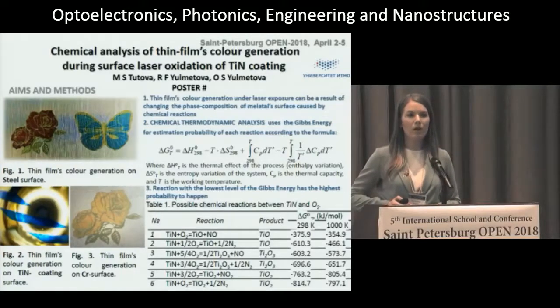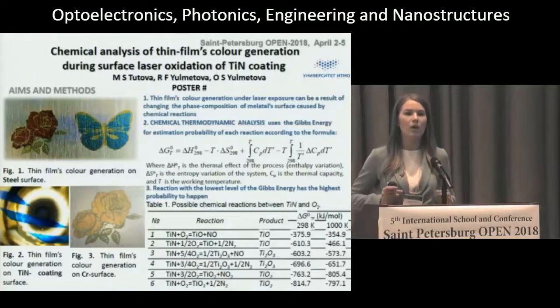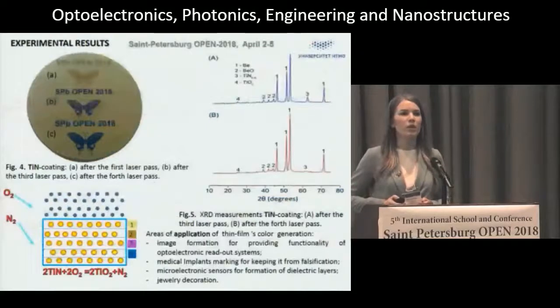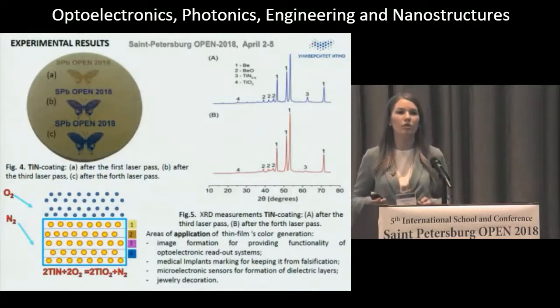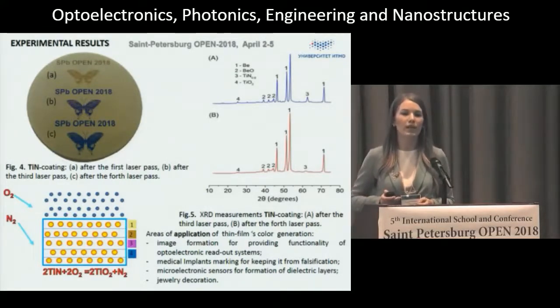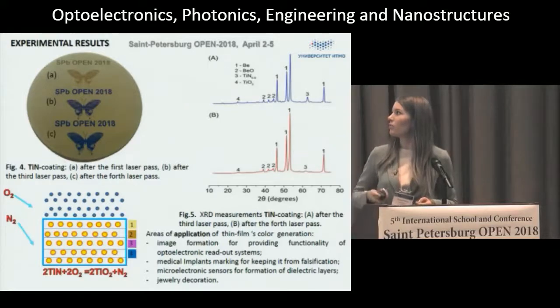According to this method, color generation can be described by a chemical reaction, and the formation of the most probable compounds has the lowest level of Gibbs energy. We tested our method on a titanium nitride coating, and the results of our calculations are in good agreement with the phase compositional analysis. During experiments, we revealed one mode that can change the color of the titanium nitride coating from golden to blue by changing only the number of laser passes. This phenomenon